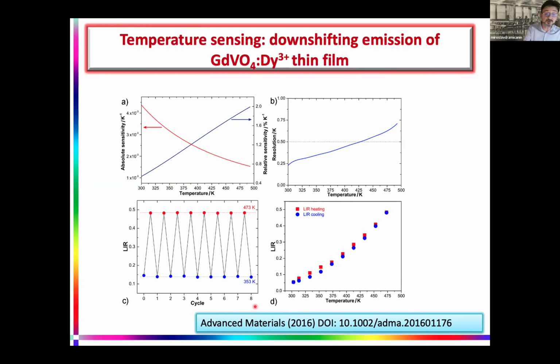So basically, we generally use this sensor today. It was successful. We have a gamma radiation facility. I know that there is one also in Latvia, and we are able to measure temperature in a harsh environment, in a strong radiation field, even without any excitation, because the radiation field induces luminescence, and we are able to measure temperature at the places where we irradiate our samples.